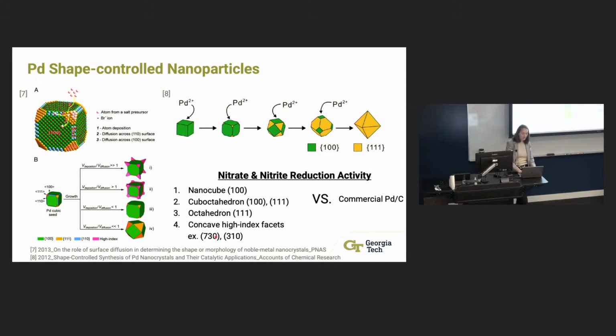Well, there's a lot of thermodynamics associated with how these will grow. Basically, one thing is trying to look at diffusion versus deposition of atoms, so you tune the synthesis to tune the deposition versus the diffusion of the atoms. But then to guide that, we also introduce other things like surfactants and ligands that will thermodynamically adsorb to one surface, and that blocks that surface from growing. Because it can't grow that surface, it has to grow in the other direction. So it's also tuning those surfactants and the binding to the surfaces. So that's how we grow them.